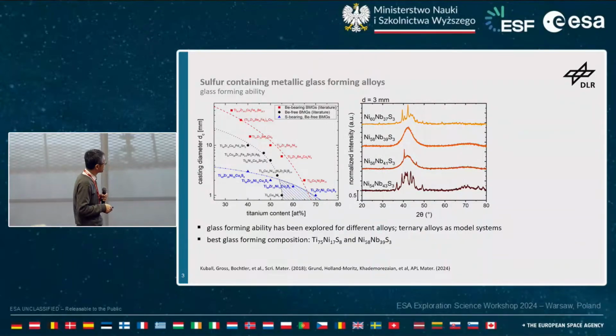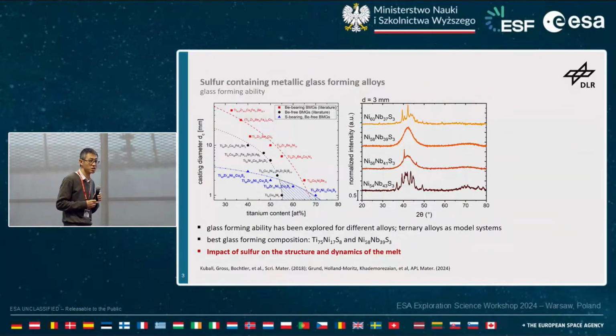This is how they did the nickel-niobium-sulfur system. First they looked at different sulfur concentrations, and once you find a good concentration range, we moved to optimize the nickel-niobium-sulfur ratio, and then we end up with these two candidates, which have the best glass forming ability. In this case, especially for the experiment on the space station, we are interested in the sulfur effect, its impact on the structure and dynamics of the liquid.